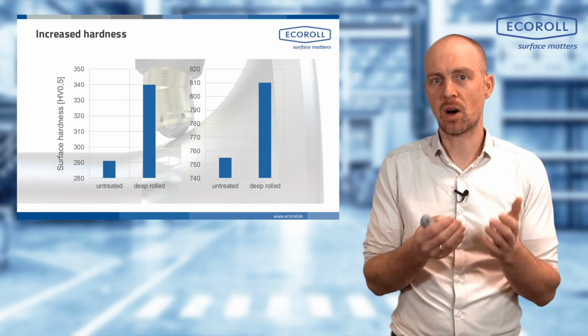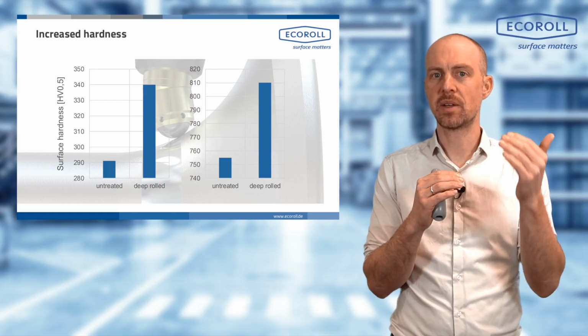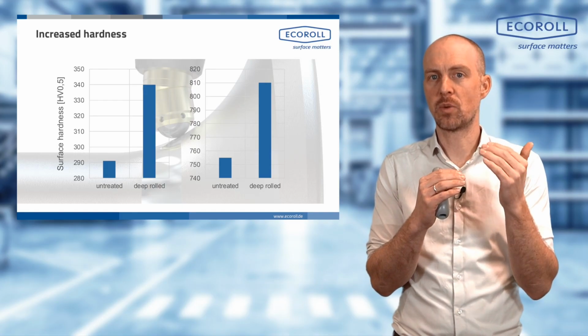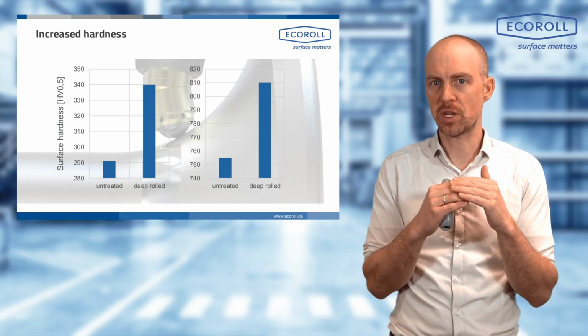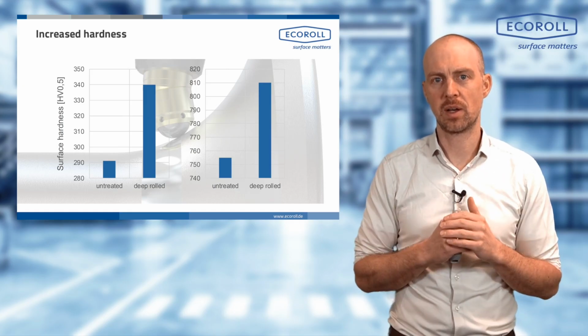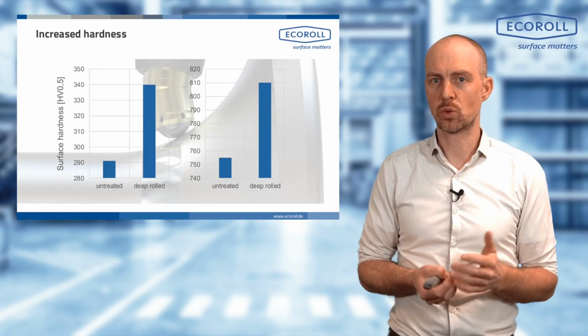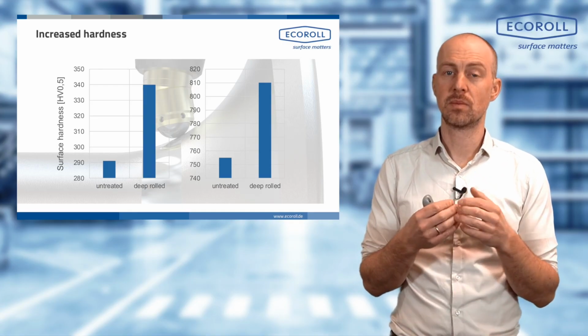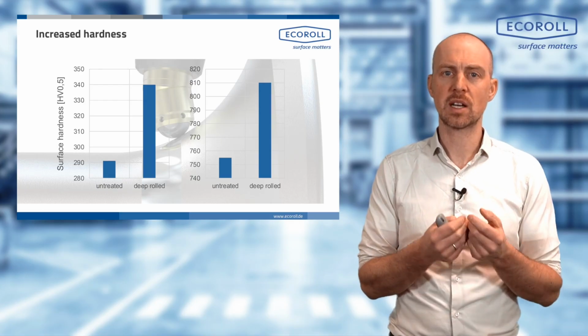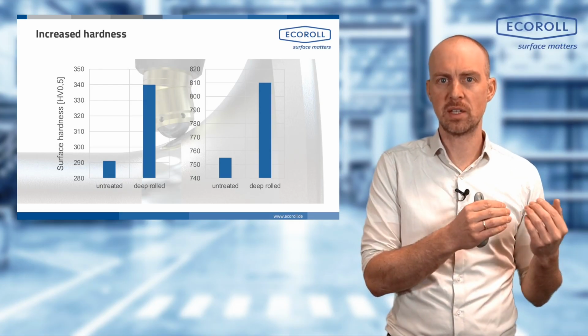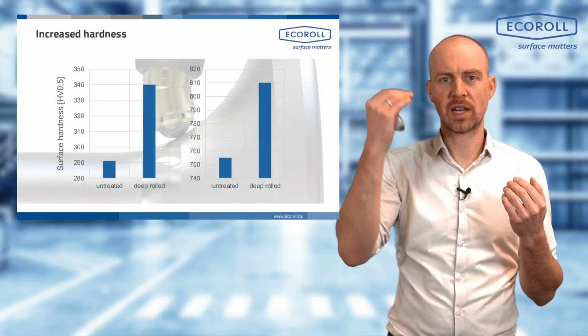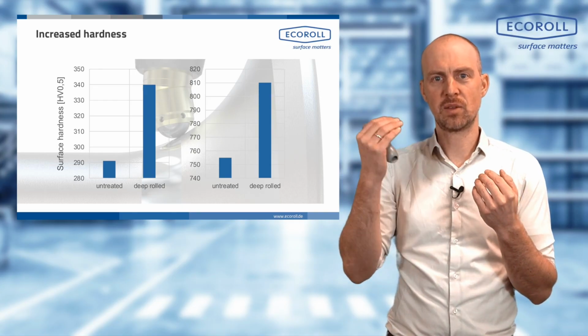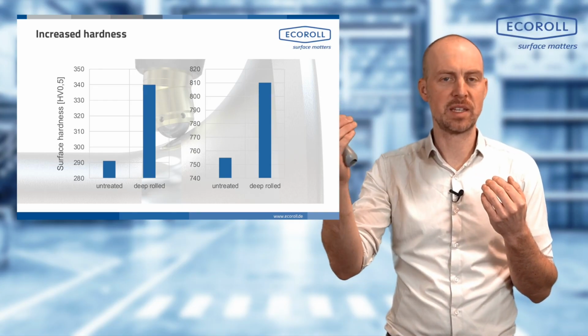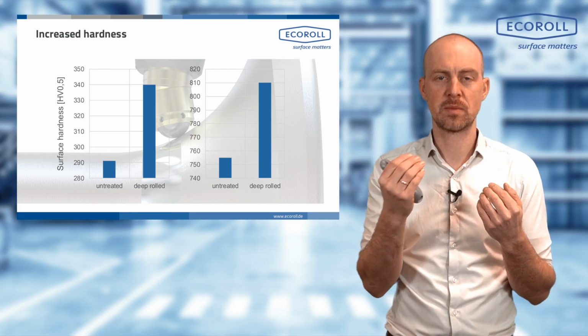I can increase my hardness very locally within the near surface area. If I want to increase wear resistance, for example, abrasion resistance in the case of abrasive wear, I can also achieve that through deep rolling. What I cannot achieve through deep rolling is a hardness increase from a soft steel to a very hardened steel. So I definitely won't achieve rolling bearing quality with a 100Cr6 if I simply deep roll it in its soft state.